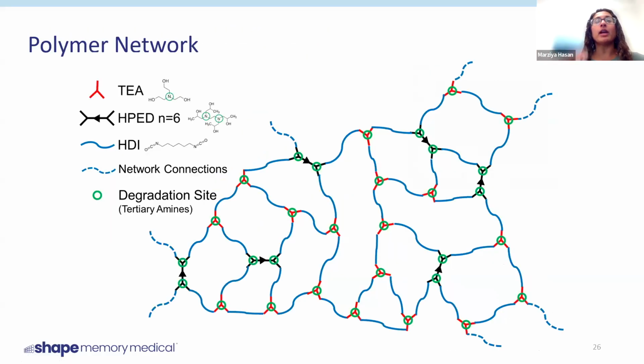And what we found out further through additional academic research is that these tertiary amines in our trifunctional and tetrafunctional polyols are what were the points for degradation. So any of these points that are circled in the green is where our degradation was taking place oxidatively. These linkages were getting broken, and then the degradation byproducts are just getting removed from the body through your urinary tract.